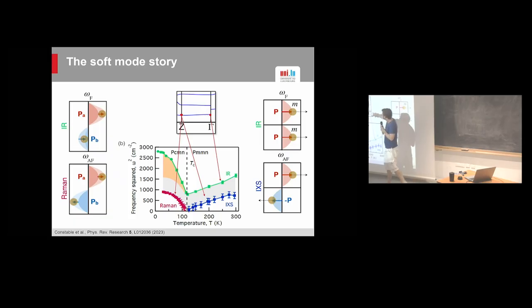If I want the mode at gamma, well, gamma is easy with optical techniques, so we could do IR and terahertz, and this is what would give you this mode here. That does soften a little bit, but it doesn't get to 0, and then it hardens again. But for the Z point, in the low symmetry phase, symmetry allows it in Raman, so this was quite easy to measure. But above, it's at the zone boundary, so you can't access it anymore by optical techniques. This is where we needed to go for inelastic X-ray.